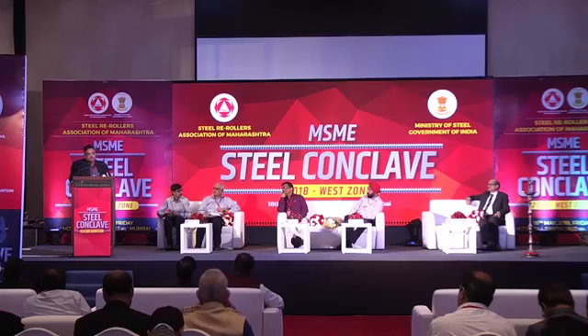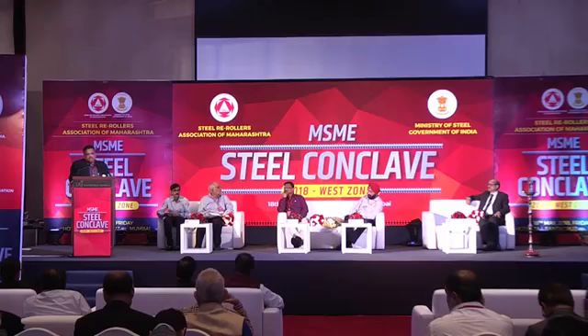Now within the secondary also, given what has happened to the electrode cost, I believe induction furnace is the only solution. And therefore, my recommendation here is that today a million and a half tons is also a size for induction melting furnace plants; integrated induction melting plants have become a reality in the country, and therefore some incentives can be given to set up large mini steel plants through the induction route. Let us say we can fix a base of maybe 0.3 million, 0.5 million, something like that. And then some incentive is given for setting up a greenfield induction-based steel plant, because this capacity can come up very quickly, and the long products can be rolled out very quickly from there.